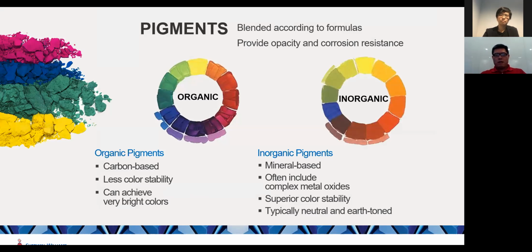And now we talk about the pigment, all right? We have so many different types of pigments. We talk about the organic pigment, the inorganic pigment, and sometimes special effect pigments, okay? So when we talk about solid colors, we color match with the organic pigment or inorganic pigments. Organic pigment is carbon-based and has less color stability. We can achieve very bright colors from organic pigment, but since it's less stable and very sensitive to heat, it's very difficult to manage during the coating process.